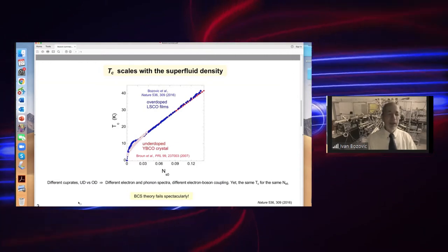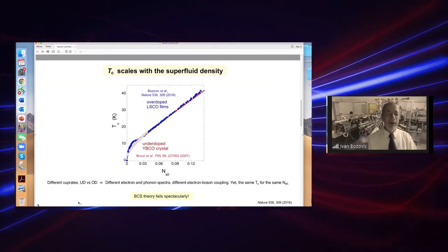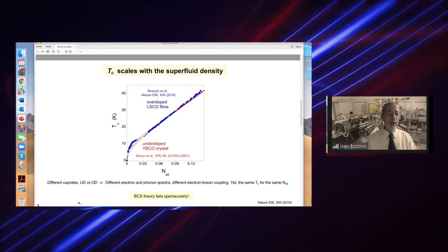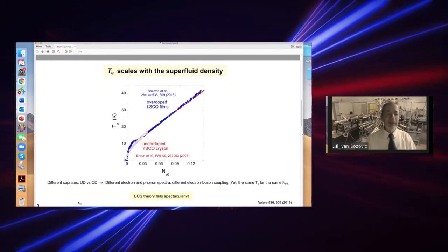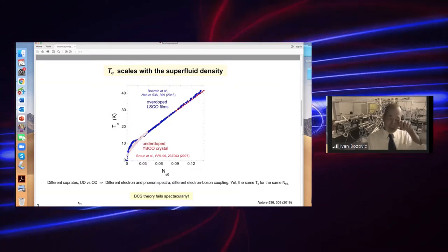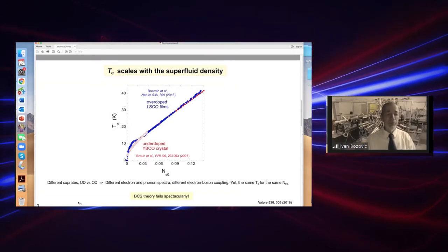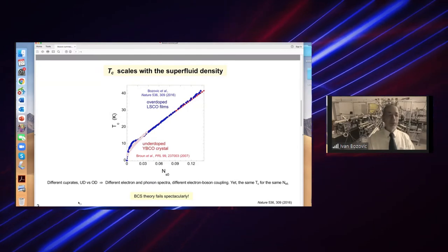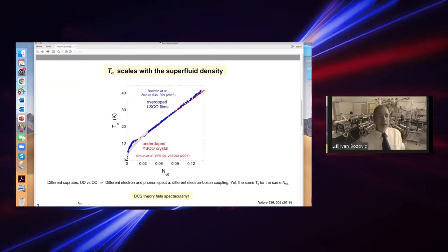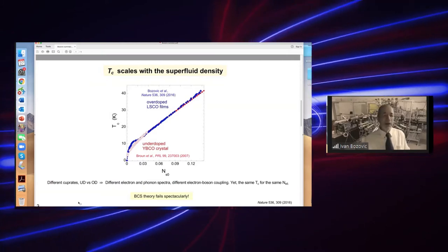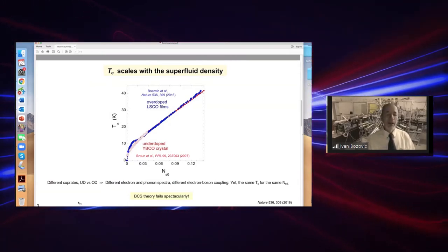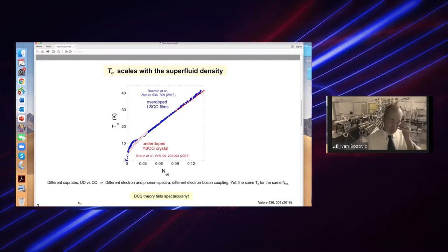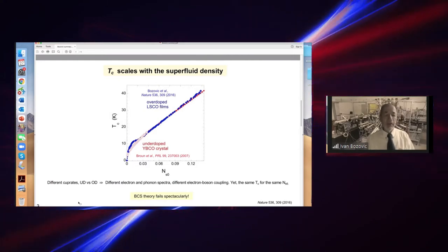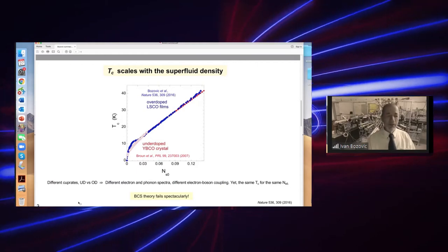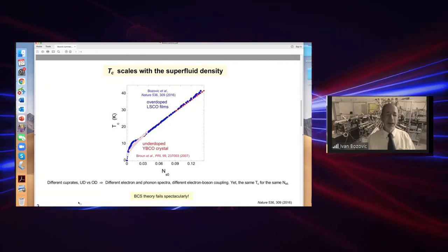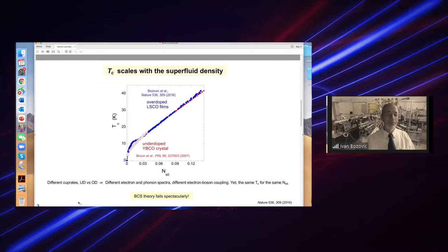Importantly, an almost identical dependence has been seen in different cuprates. Apparently, in cuprates, Tc does not depend on the details of the electron spectrum, nor of the spectrum of phonons or any other bosonic excitation that may be relevant, nor on their coupling, and not even on whether the cuprate is underdoped or overdoped. This indeed contradicts the most basic tenets at the essence of the BCS theory.